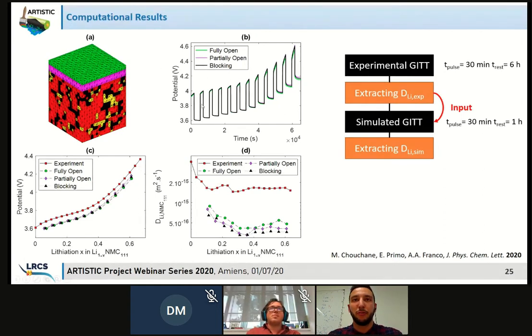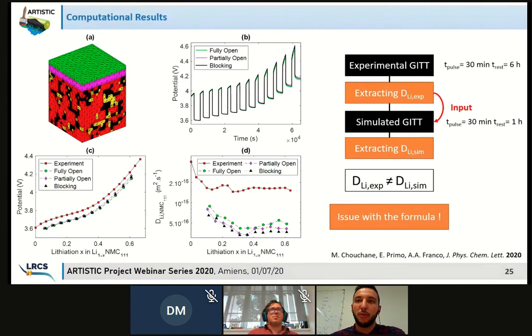So here are the different results we got. Once again, we applied these three hypotheses workflow: blocking, partially open, and fully open. As you can see here, this OCV curve, which was extracted from experimental and modeling, is quite in accordance, in agreement with each other, I would say. However, when you look at the extracted lithium ion diffusion coefficient, you see there's a factor 5 difference between the two, between the experimental one and the simulated one, which means there is an issue with the formula, obviously.